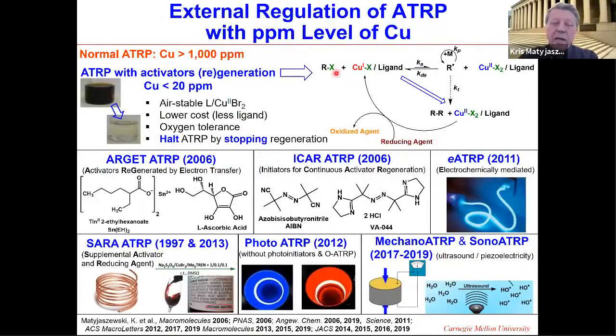So let me come back to these processes which are run now not with 1,000 parts per million of copper, but 10 or 20 ppm of copper. So this is a big improvement. And in fact, it allows us to work now with a very low concentration of copper, but we cannot prevent radical termination. Any act of radical termination will oxidize irreversibly copper 1 to copper 2, and the reaction would essentially stop. So we need to regenerate these species.